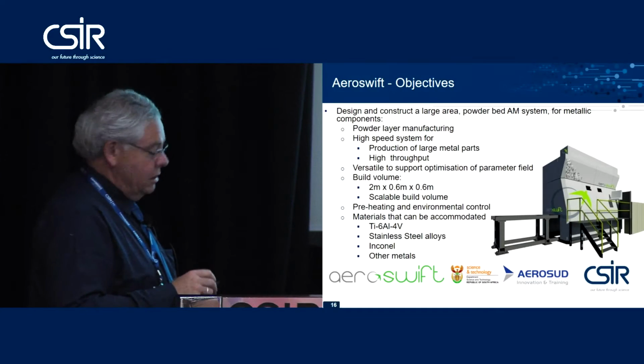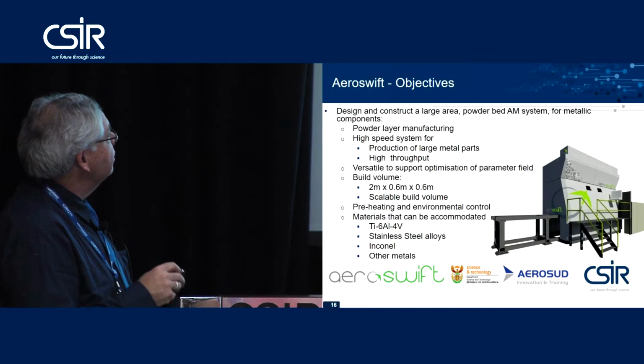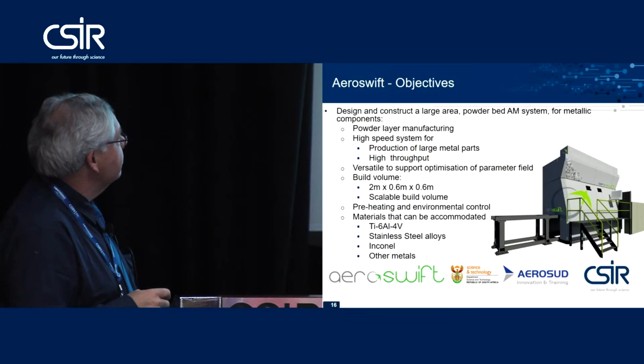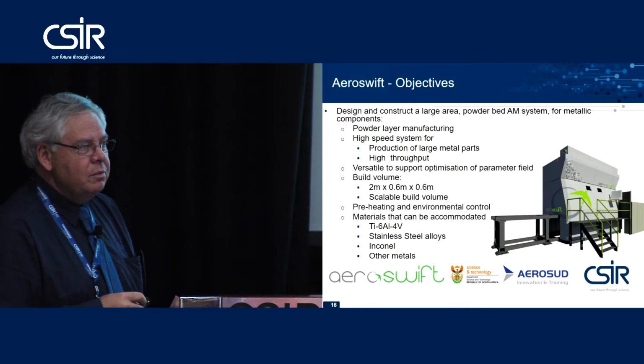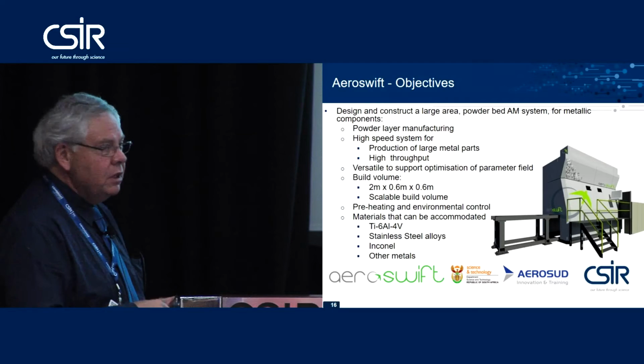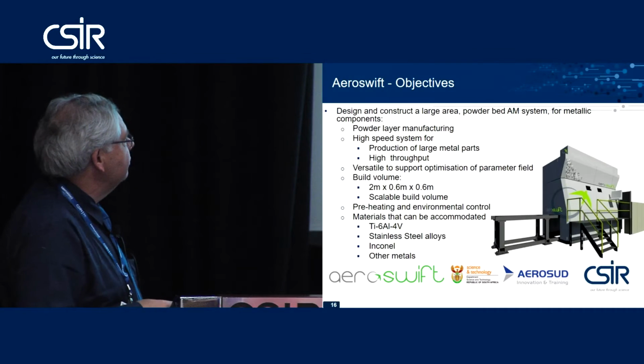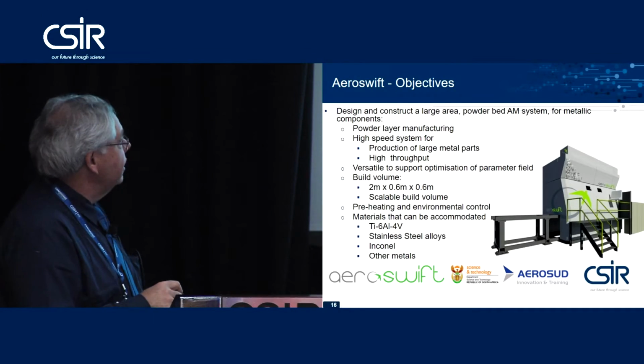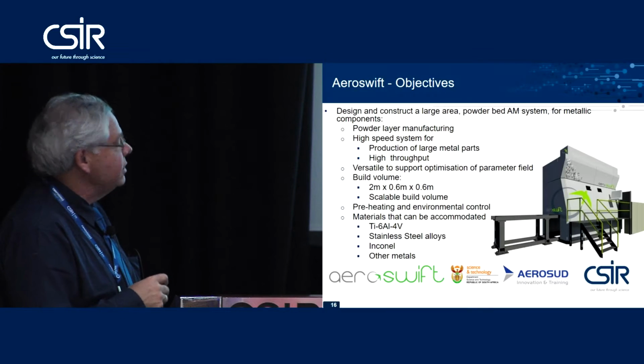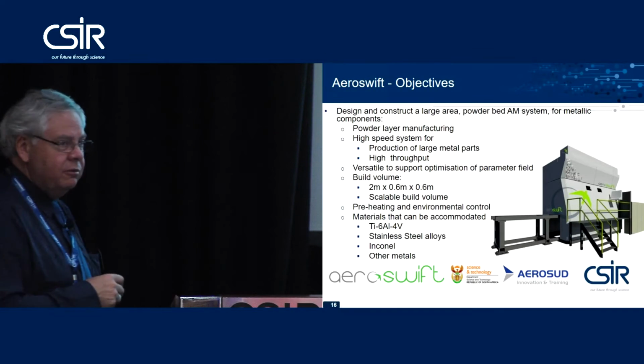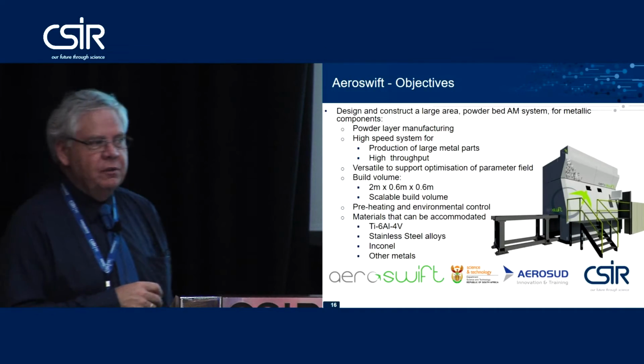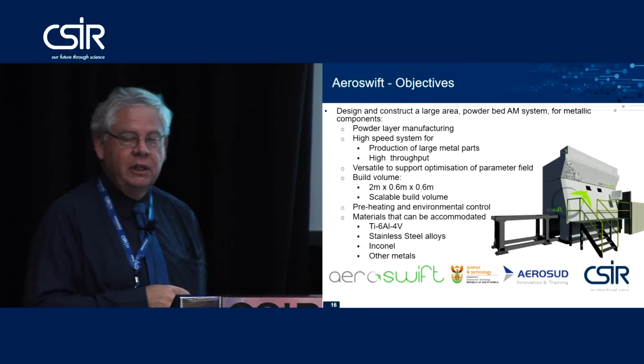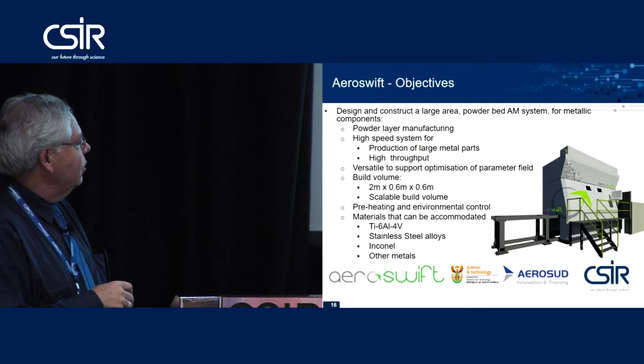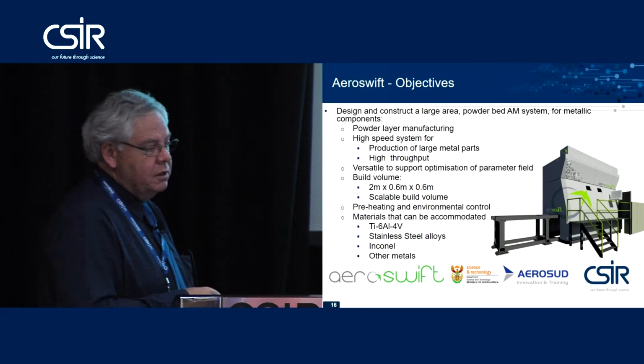So the system as it's designed has a build size of about 2 meters by 0.6 by 0.6. We have also made this scalable so that we can decide to have smaller bed sizes if required. And the machine is designed to allow us to process Ti-64, or titanium 6 aluminium 4 vanadium, which is the alloy of choice not only for aerospace but also for medical applications, stainless steel alloys, Inconels, as well as other metals.